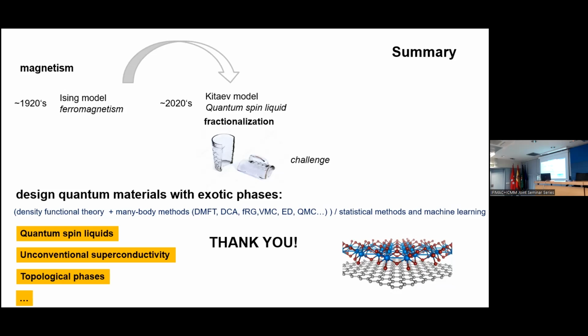More questions? Yes. So, would you say then that alpha-RuCl3 is the best candidate for the Kitaev model, or do you think there is another material? So far it is the best candidate, and that's why in this construction here, the interactions that spoil the spin liquid are that the ruthenium-ruthenium are very nearby, so you have a lot of direct interactions, and you just don't want them. So what you want is to blow up the structure. If you blow up the structure, you kill these interactions, and the ones left are the Kitaev ones. And what we saw here is that when you do this construction, we go more and more into this Kitaev limit. And this model that I was showing you was assuming that it is in the Kitaev limit. So still, this is one of the best candidates when you manipulate it.